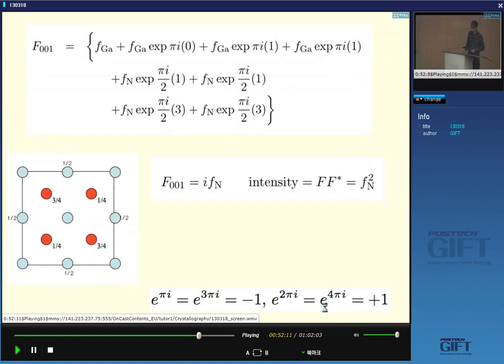So now I'm going to look at gallium nitride structure where we have two different kinds of atoms. So you've got a gallium atom at 0, 0, 0 and a nitrogen atom at a quarter, quarter, quarter. So it's similar to what we did before. It's cubic F, but the motif now consists of a gallium atom there and a nitrogen atom there. Now I definitely need 8 separate terms because the atoms are no longer identical, and I can't simplify the equation as we did with the lattice times the motif. So I have here the 4 gallium terms corresponding to the atoms at the corner and at the face centers, and I have 4 nitrogen terms corresponding to these over here.